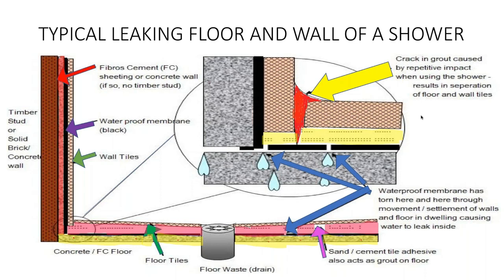Contrary to popular belief, cement is not waterproof — it is porous. If not treated properly it will absorb water. Looking at the yellow arrow at the top right, that is the exploded view of the shower corner. The red area shows where small hairline cracks develop at the corner of the shower floor and wall, because the wall is built first and then the topping is placed against it. The best solution is to have your floor going in underneath the wall. When repairing, cut out the tile and plaster down to the brick, then cast the new floor topping going in underneath, directing water towards the drain.